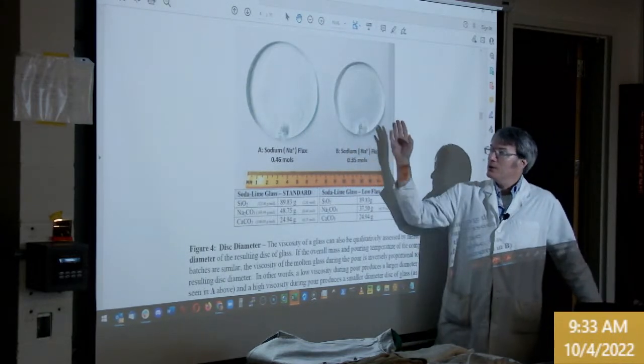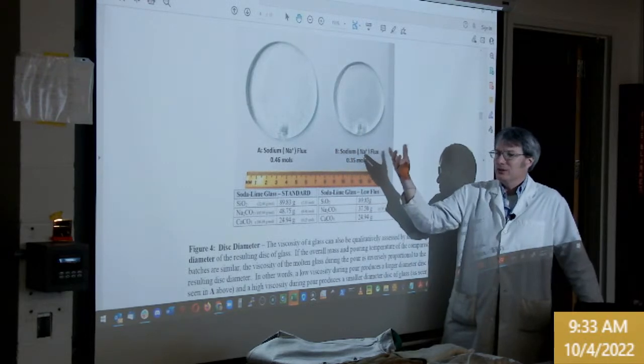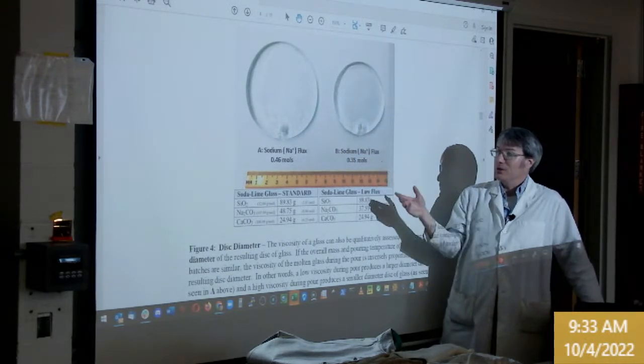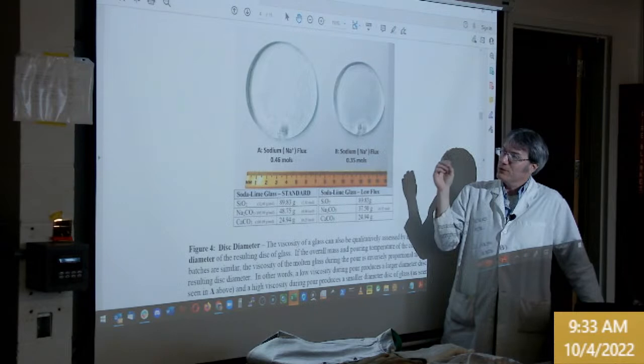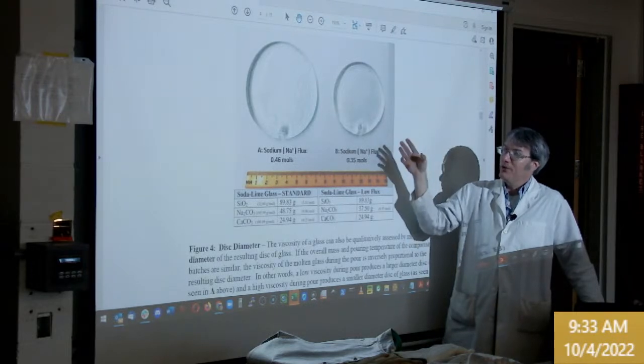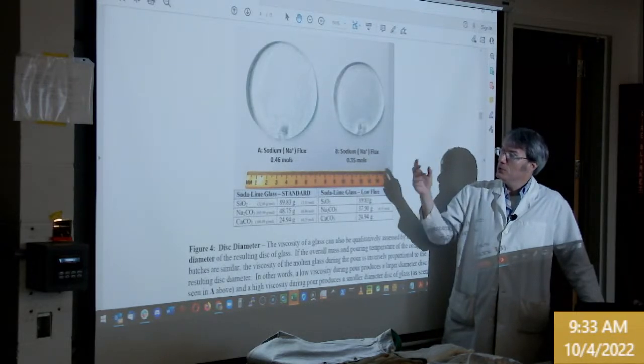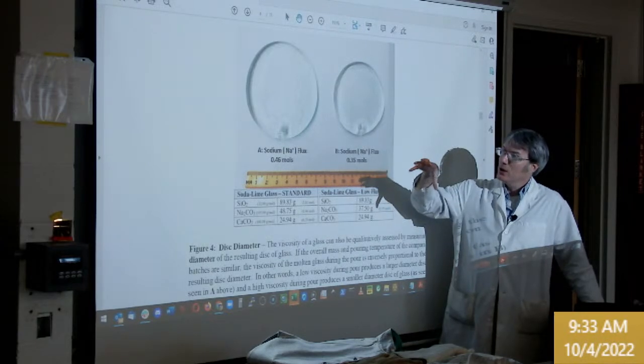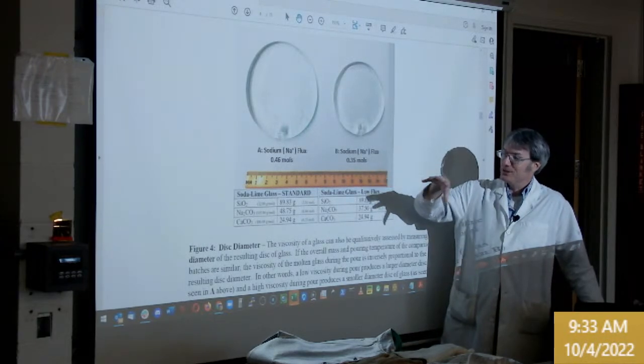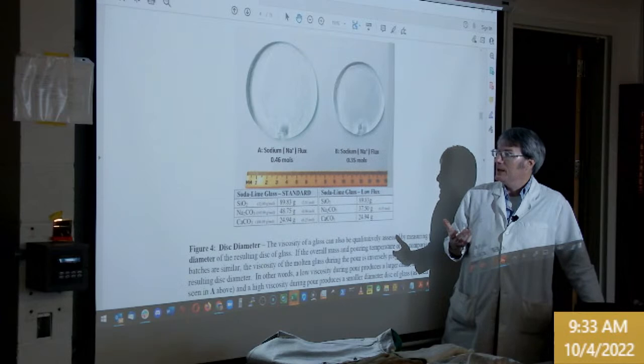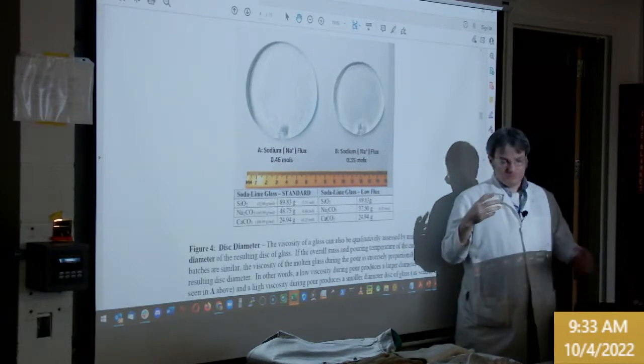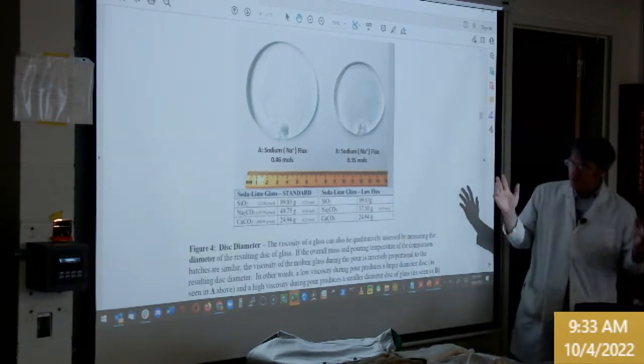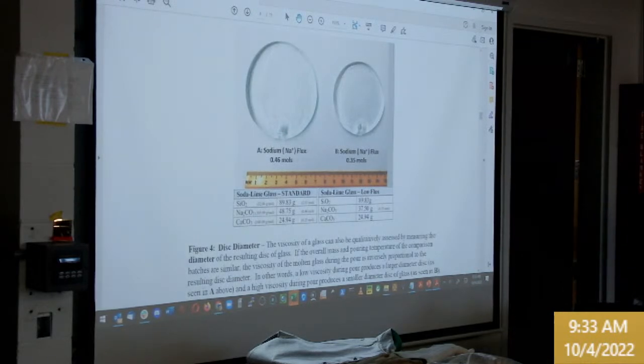So we're going to try to relate, since we're not actually doing viscometer measurements on the glass, some of the remnant artifacts of the pour to viscosity. And so the diameter of the glass disc becomes a pretty good way to semi-quantitatively or qualitatively assess the viscosity during pour.